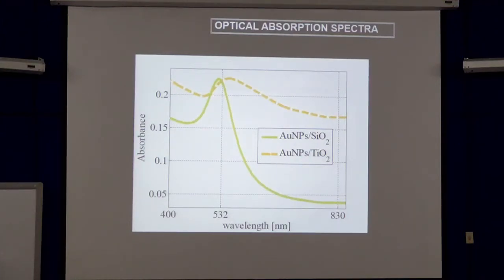if you see the right part of the absorption bands or the surface plasmon resonance, you're going to obtain a sign, for instance a negative sign, in the response of the nonlinear optical refraction. And in the other one, if you use a wavelength for the other slope, you're going to change the sign, so it's going to be positive. For instance, negative refraction can correspond to thermal, and positive can correspond to electronic. So you can change the mechanism of the interaction with the light and the material by changing the surrounding.